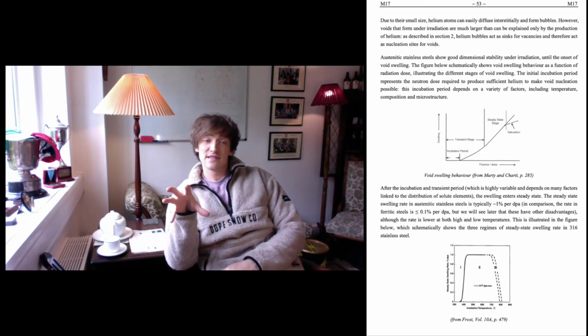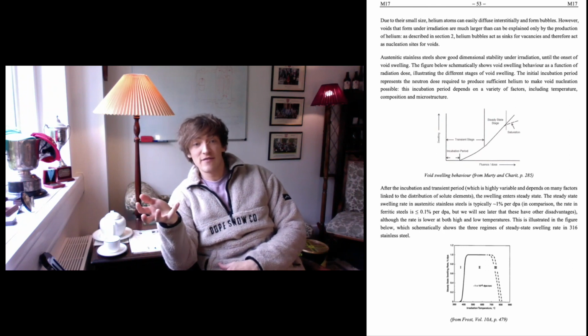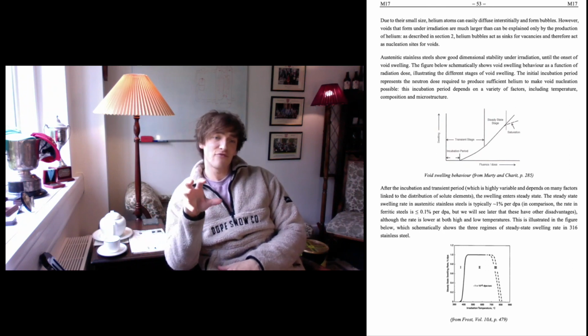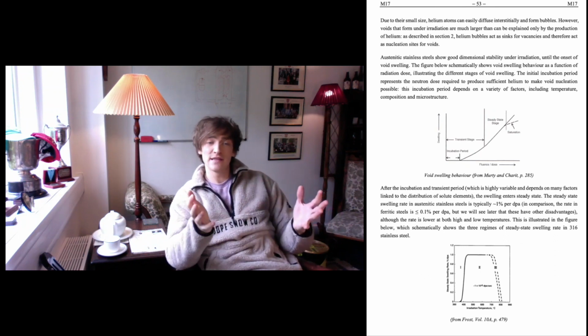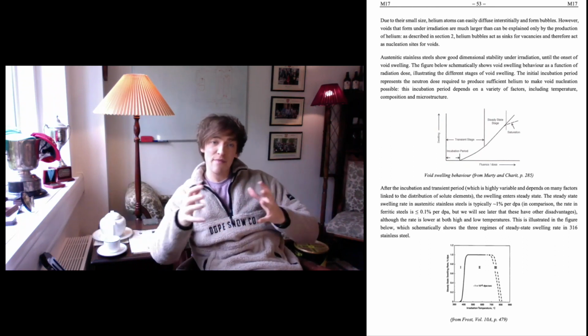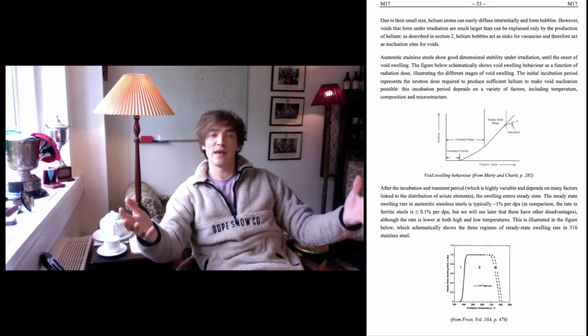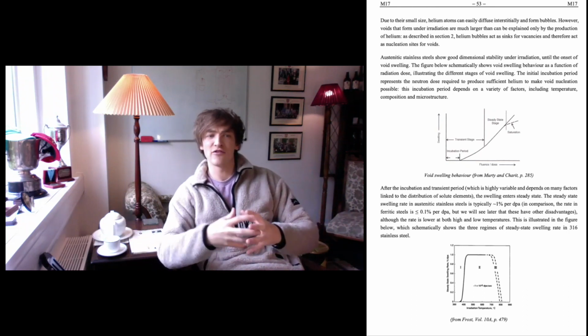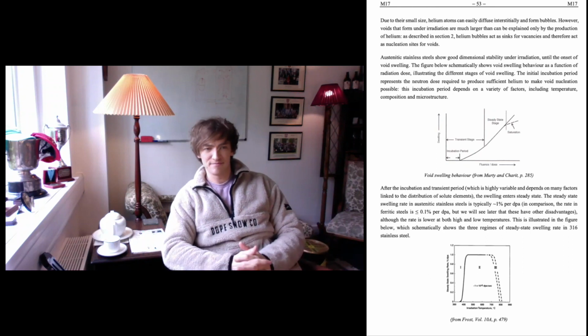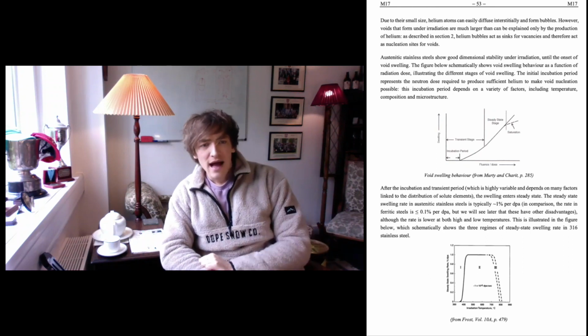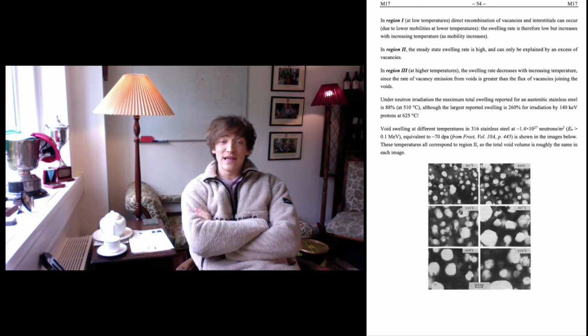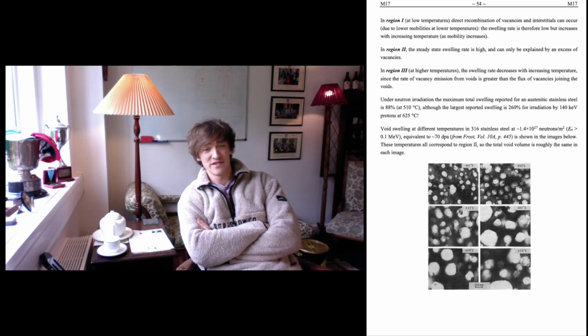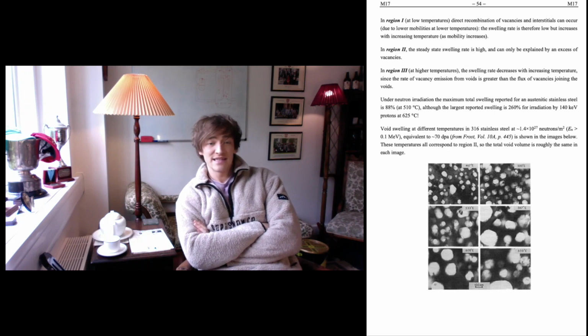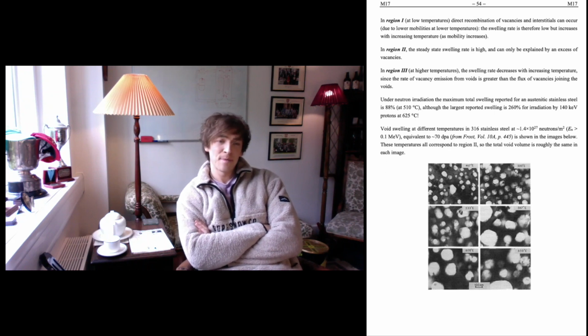And at high temperatures, the swelling rate decreases again with increasing temperature, since the rate of vacancy emission from the voids is greater than the flux of vacancies joining the voids. So they're battling each other, but when you get to high temperatures, more are being emitted than the flux coming in to grow them. So the swelling goes down. And that swelling can be incredibly large, up to 88% by neutron irradiation, although you can get hundreds of percent should you choose to massacre your material in a proton beam experiment.